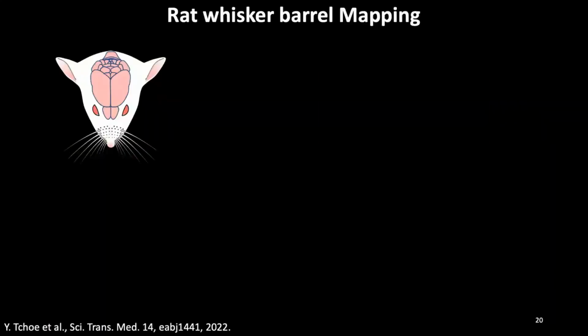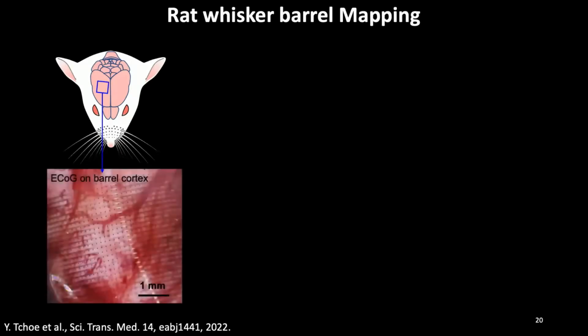So we'll start with mapping in a gold standard experiment where we know that there is organized distribution of cortical columns. This is the whisker barrel experiment. We place a grid with spacing between the contacts of 150 microns, covering about 4.5 by 4.5 millimeters, and we bring a small tube and do air puffs on individual whiskers. We want to evoke activity in the sensory motor cortex that corresponds to that individual whisker.